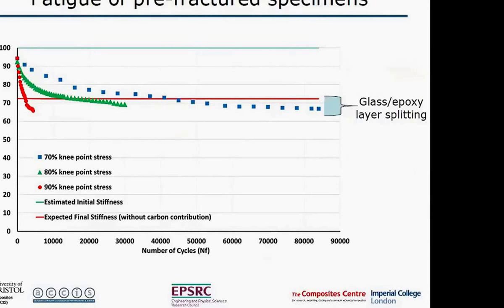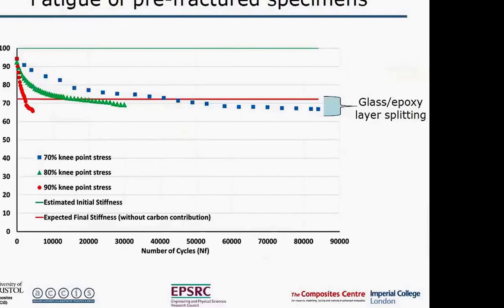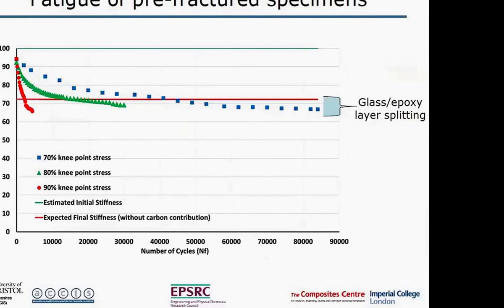So under fatigue loading, then, it is sensitive. But if you keep that strain low, the whole premise of this program was we want to be operating on that initial margin, on the initial linear slope. The nonlinear response is to give us some margin. If you exceed the limit, you get the load redistribution. But actually, we want to be operating largely in that linear proportion. And if you stay within that, keeping the stresses and strains relatively low compared to that knee point, then you've got no trouble with fatigue either.